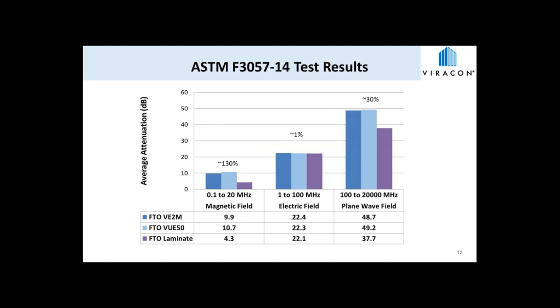So, summarizing the results, this shows the average attenuation for each sample when split up into 3 main categories: the magnetic field from 0.1 to 20 megahertz, the electric field from 1 to 100 megahertz, and the plane wave field from 100 megahertz to 20 gigahertz. This really shows the big influence that the addition of the Low-E coating has on attenuation, ranging from a 130% increase at the lower frequencies to only about 1% in the electric field, as it holds pretty close to the RF units. But where most electronic devices operate today, the addition of the Low-E coating gives about a 30% boost in attenuation, which, keeping in mind the logarithmic nature of attenuation, is pretty significant.